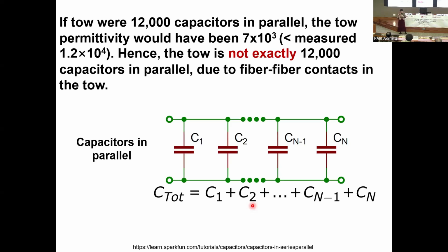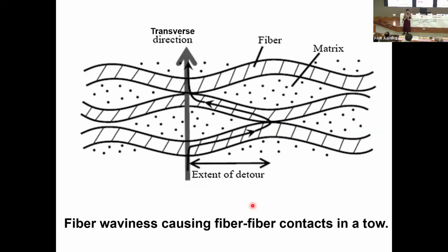Now, if that tow were 12,000 capacitors in parallel, then the tow permittivity would have been 7 times 10 to the 3, which is less than the measured value. Hence, the tow is not exactly 12,000 capacitors in parallel, and that's because of the fiber-fiber contacts in the tow. And this is what I mean by the fiber-fiber contacts enabled by the fiber waviness.